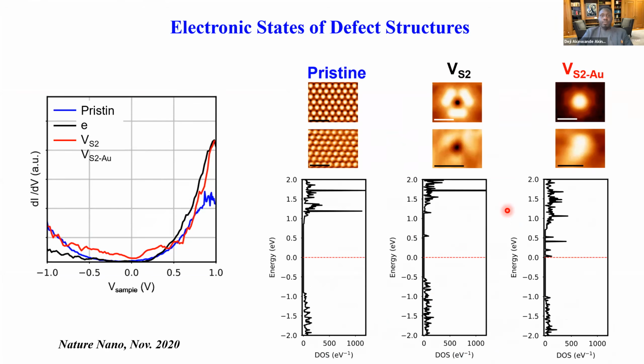It's not every time. According to statistics, it's about 1/3 of the time. That's quite a lot. Yeah, so it's about 1/3 of the time. The majority of times, if you do a high voltage transport, we don't see the effect. So there's still some trigger phenomena that we don't understand - why we see it in some cases, why we don't in others. But on the other hand, when you're trying to get rid of the gold atom, that is more predictable. I would think it's easier to pick it out.